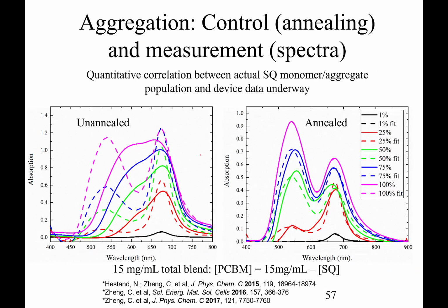What we've tried to do is quantify how much material we've got, how much aggregate we've got, and how much monomer we've got. So if we look at these annealed spectra on the right hand side, what you can see is that when we have 100% squaraine sample, we've actually got, we claim, and we think we have pretty much 100% aggregate in the spectrum. In the spectrum we see this characteristic double humps. There's a peak here and a peak here in the spectrum. So we claim that this is our annealed spectrum. This is the spectrum of the aggregate.